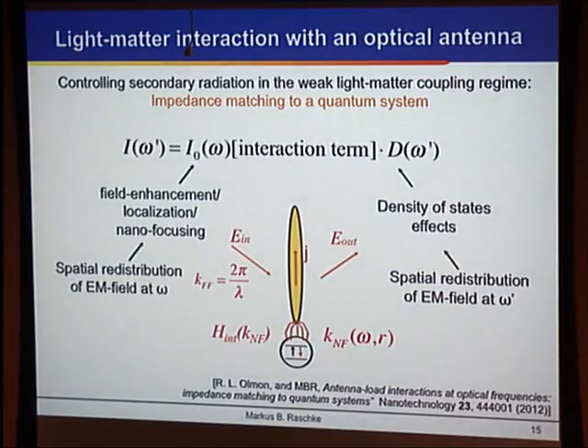But it actually turns out it is because you have increasing density of states the sharper you make the apex, which you can again picture in terms of that we get larger and larger momenta, which then couple with a larger and larger momentum space of this point dipole. Right? And so this is why, in the analogous language of antenna physics, we are doing some impedance matching here through this coupling from a point dipole to this large momentum space, and therefore really what we're doing here is controlling the antenna load interaction at optical frequencies.